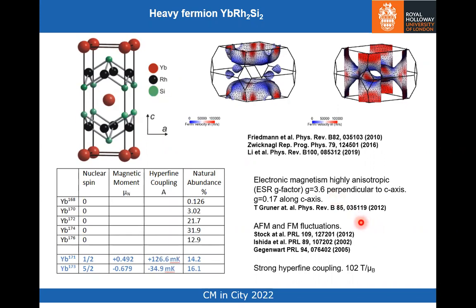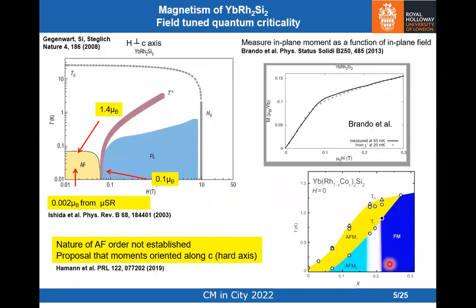Then there's all this work which indicates that the system exhibits both antiferromagnetic and ferromagnetic spin fluctuations. The presence of ferromagnetic spin fluctuations in this system is somewhat undersold, I would say. So that comes from neutron scattering. It also comes from NMR and measurements of the magnetization. And the other key characteristic that distinguishes it from cerium-based heavy fermion materials is that there are these species with nuclear spin that have an extremely strong hyperfine coupling of 102 Tesla per mu B. So mu B would be the effective moment on the effective local electronic moment arising from the 4f electrons.